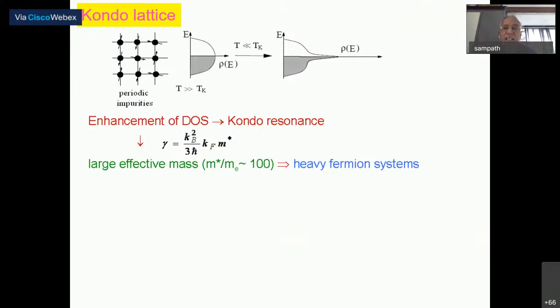Now, when you come to rare earths, it was believed four or five decades ago that in principle you can have the Kondo effect in a concentrated system, that is, at every site you can have the Kondo effect. The reason is that it was believed that 4f orbitals do not overlap at two different sites, which is not the case in a transition metal system. There is significant overlap, therefore you cannot have the Kondo effect on a concentrated lattice of transition metal. In general, there are some exceptions for that. But in general, you can expect the Kondo effect at every site. Therefore, they are called Kondo lattices.